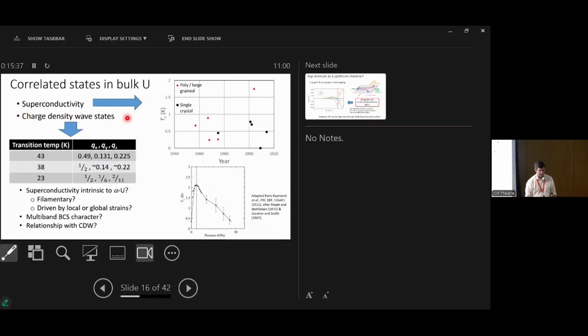So it looks like a high temperature superconducting cuprate, but it's an element. Yeah? The CDW is quite complicated. There are various transitions, various Q vectors. I won't go into that. In thin films, we can actually boost that charge density wave transition up to about 100 Kelvin. So we're using strain to do that. I won't talk about that either.